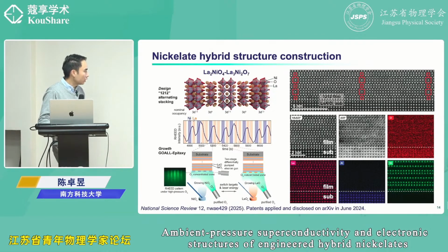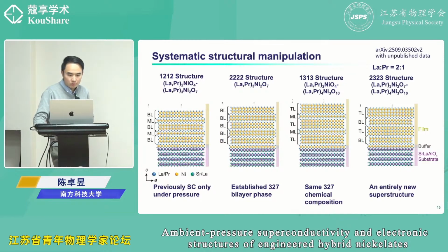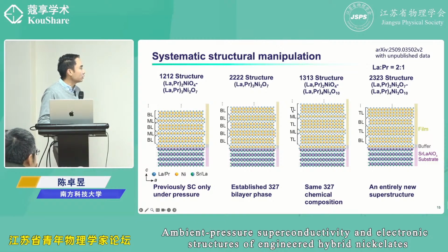Actually, in the middle of last year, we could already make this structure, but at that time we didn't get superconductivity yet. More recently, beyond this 1-2-1-2, we now call it 2-2-2-2 in this series. This is the bilayer 3-2-7 superconductor that's been established just now. We also did 1-3-1-3 and 2-3-2-3 structures.